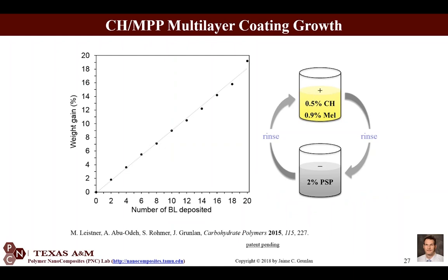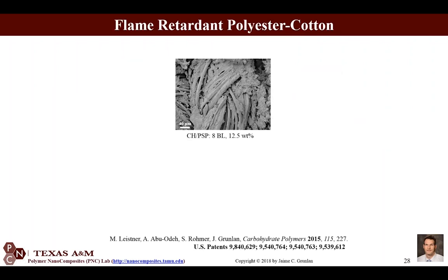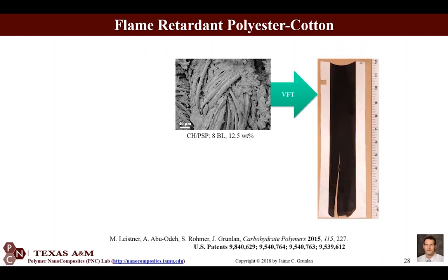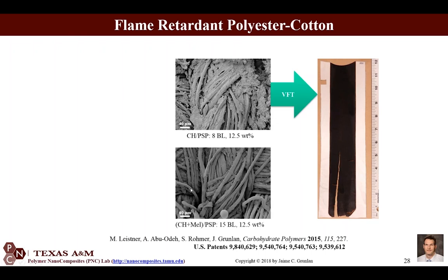That's more complicated. And so what we did was we put chitosan and melamine together in one solution and polysodium phosphate in the other solution. And we did layer by layer with that. And when you put that onto polyester cotton fabric, it doesn't pass the vertical flame test if it's just the chitosan with the PSP. So that would be something that would flame retard cotton, but it will not flame retard polyester cotton.